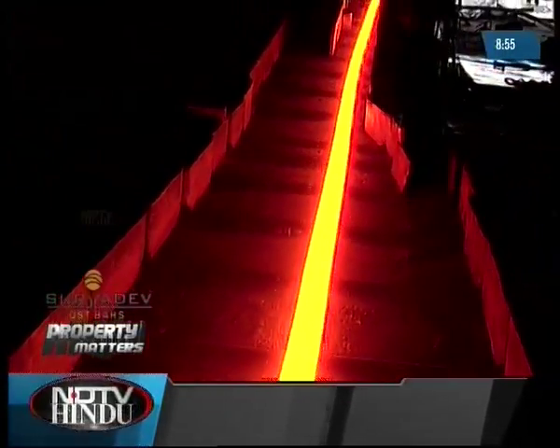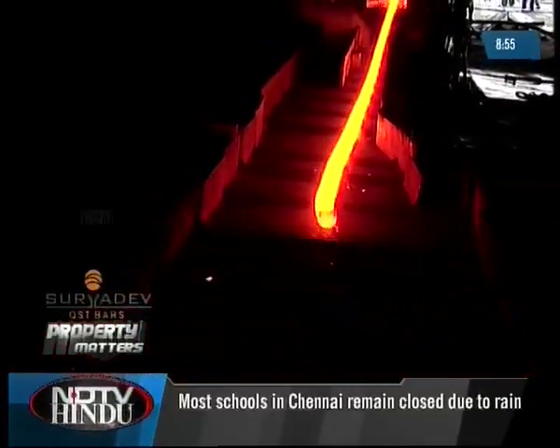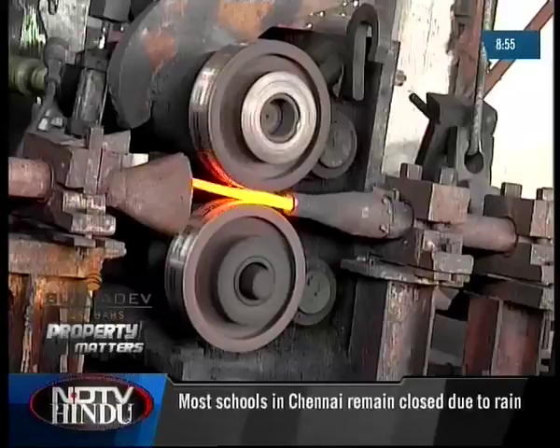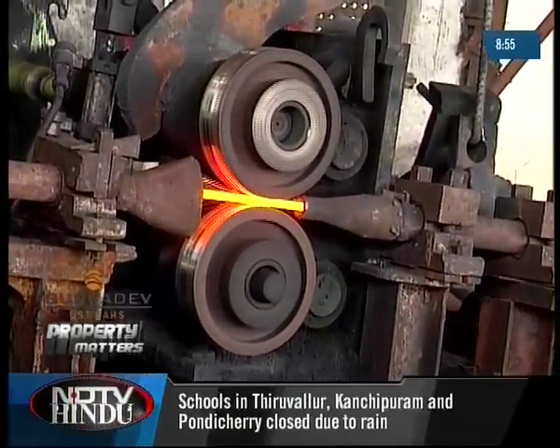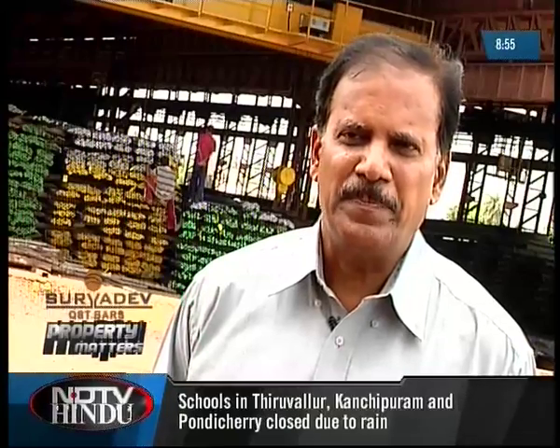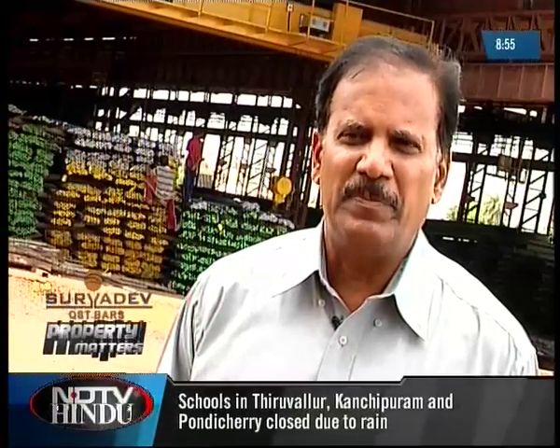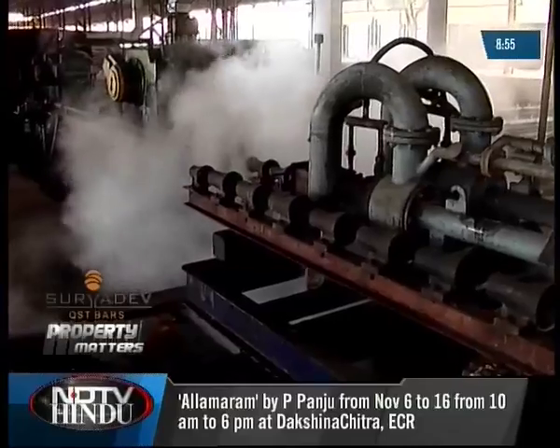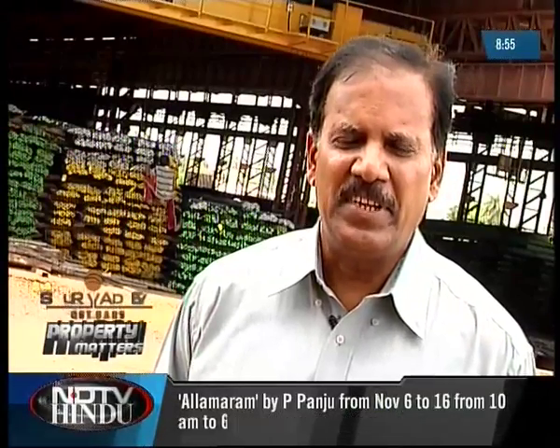After it is taken out of the furnace, the actual rolling process starts, where these billets are reduced to smaller sizes, stage by stage. We use about 23 stages to reduce the billets for reinforcement bar making. There the temperature is brought down. We strictly follow the temperature of steel so that the quality is maintained. And at the end, we have a quenching process called Thermex to introduce a thermomechanical treatment, which gives an inherent property of strength and resistance to corrosion for the finished product.